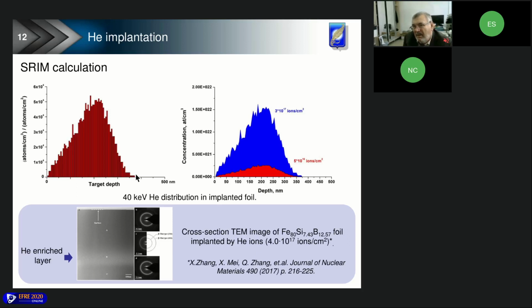Of course, using transmission electron microscopy and analyzing the sample cross-section, helium-enriched layers can be seen. For example, just like here, the helium-containing layer looks like this bright area at the cross-section of iron-based metallic layers. This layer has higher brightness just at the mean projected range.